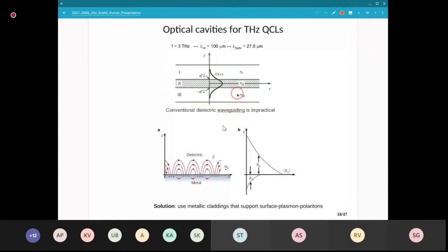Now, that would be unfeasible at these wavelengths. It's doable at infrared and visible wavelengths, but at 3 terahertz, for example, the wavelength in air is 100 micron. If we were to use gallium arsenide, it's about 30 micron wavelength inside gallium arsenide. So the dielectric layer thicknesses have to be of the order of a wavelength, or half a wavelength, or quarter wavelength.